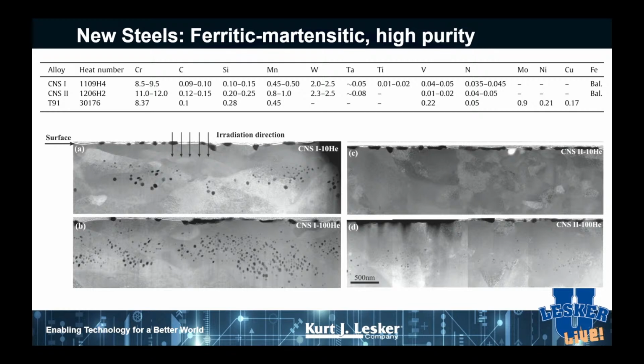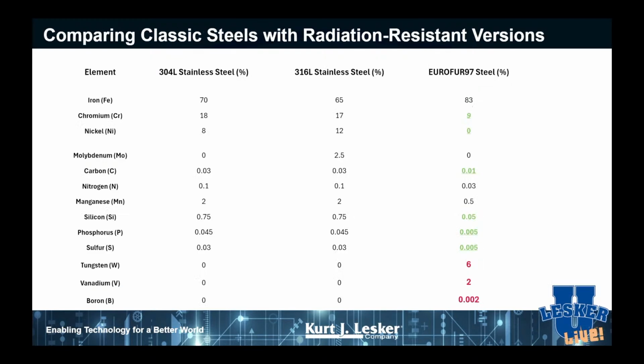Here's just some data for you. This is data from China. These are a couple of different versions of a steel that was made in China, and you can see that in terms of neutron resistance, CNS1 is not quite as good as CNS2, and I think the difference there is they removed titanium. They changed some of the concentrations of some of these bad actors, but you can see even with high doses of neutron radiation, you still see transitions in the crystal structure. You still see the beginning of some voids and other species there.